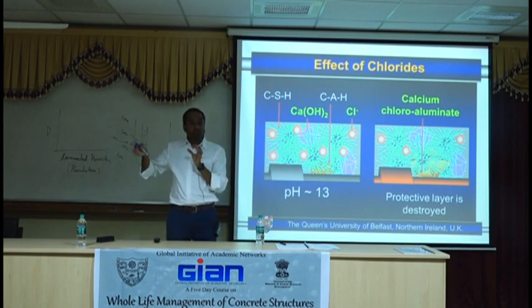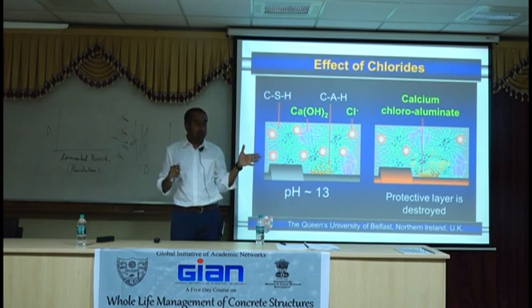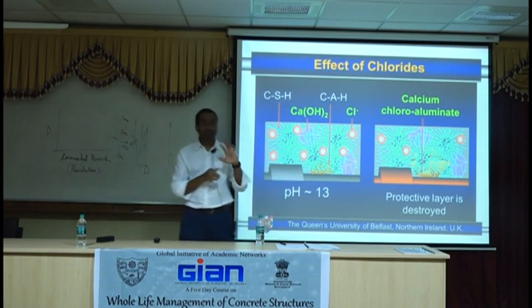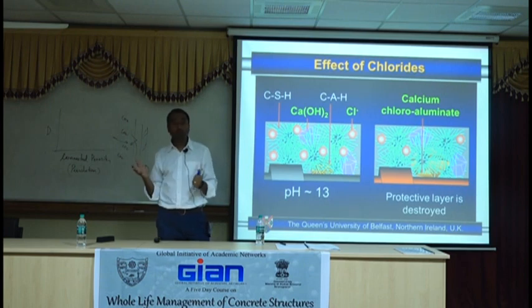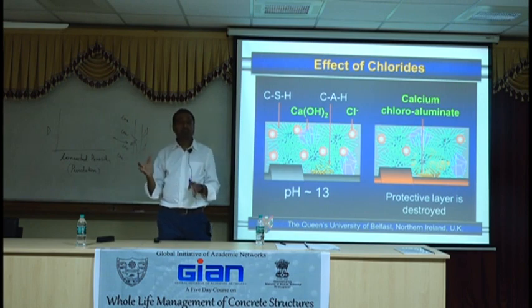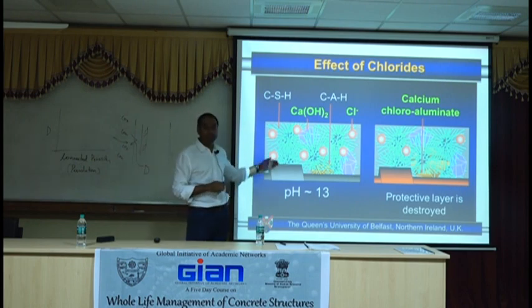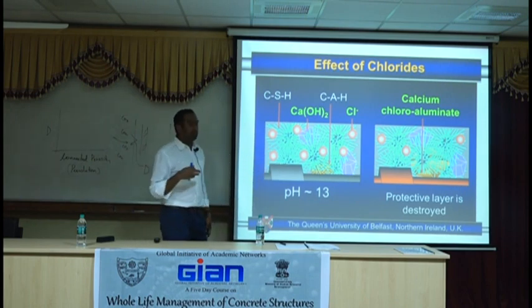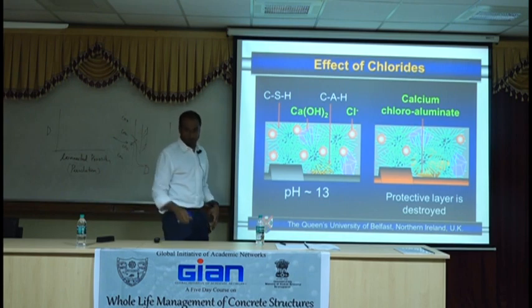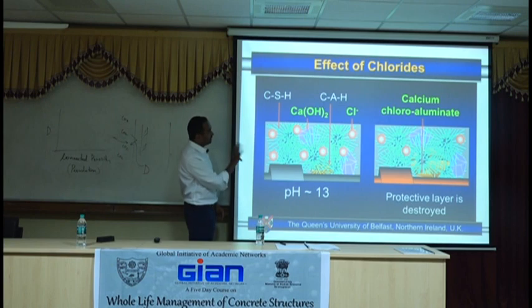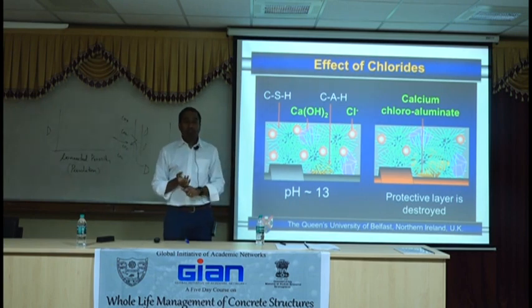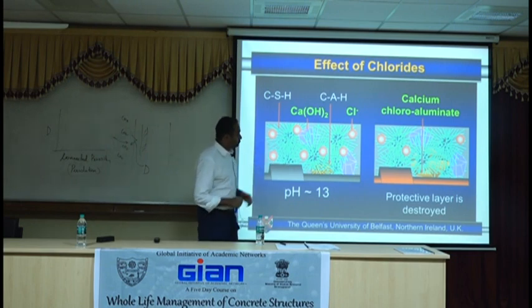And that's where the structural construction will need to be looked at. If it's precast and everything is made in a yard, they can blend anything they want. The majority of the precast in the UK use a lot of limestone fillers. Not because they have a lot of limestone, but because it's inert. And they can control therefore the reaction and the rate of reaction. And also they're using it for a different purpose, to make it flow, SCC, self-compacting. Sorry, deviating back to chlorides. So I need the aluminate phase, I need the silicate phase, and I need any other phase that I want to form the structure.